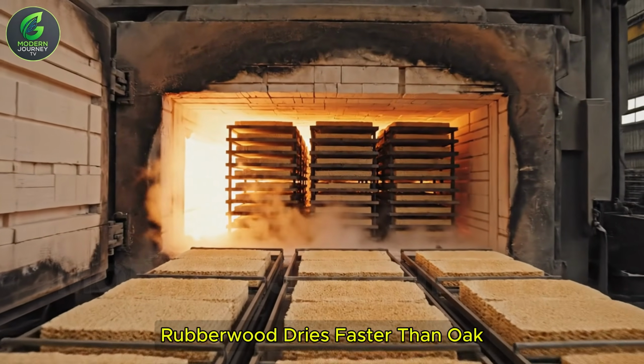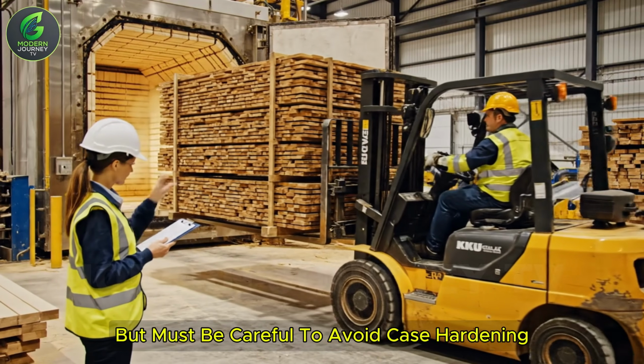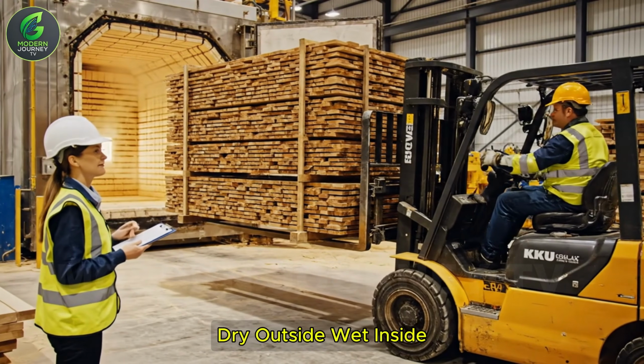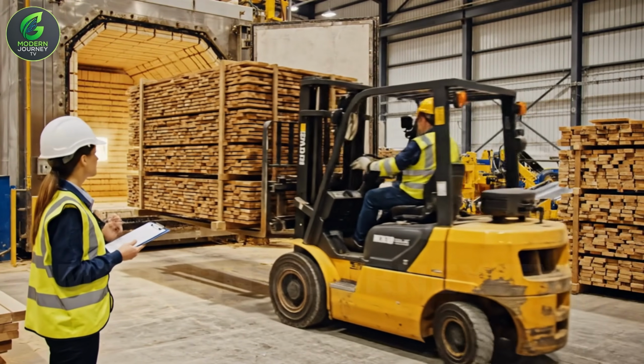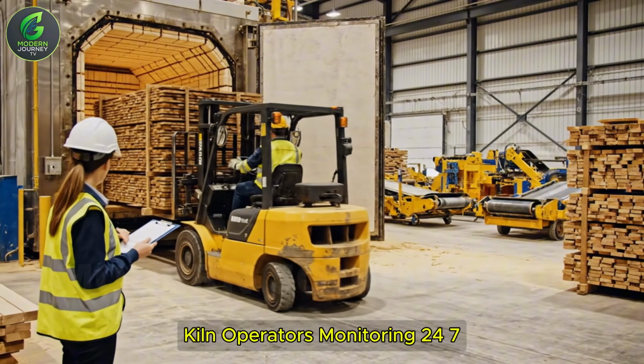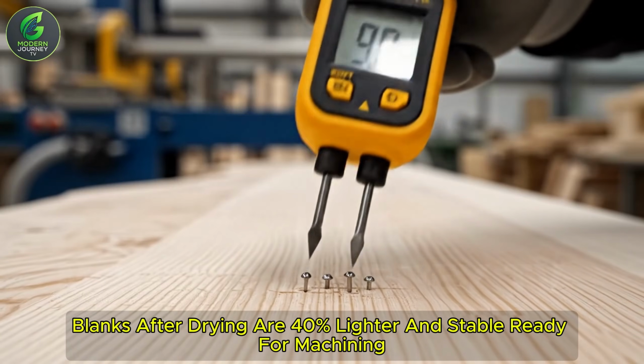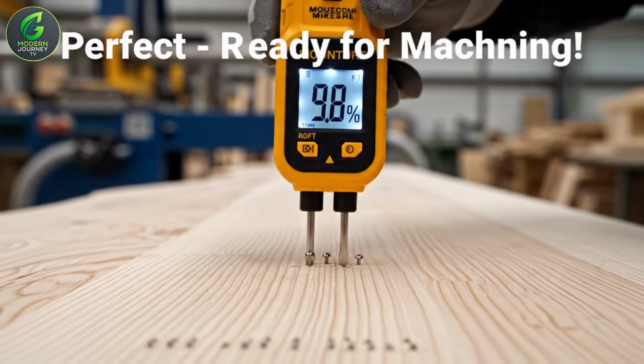Rubber wood dries faster than oak, but must be careful to avoid case hardening: dry outside, wet inside. Kiln operators monitor 24/7. Blanks after drying are 40% lighter and stable, ready for machining.